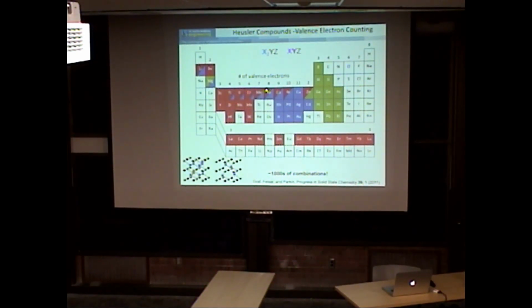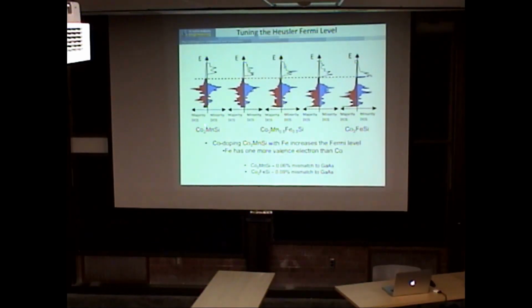If I do cobalt-2 manganese silicon, what happens if I decided to add iron, say do cobalt-2 iron silicon? I've added one valence electron to the formula unit if I did that, or go in between. In fact, we could go in between. Let's just add iron, mixing sort of manganese. I should be able to go from cobalt-2 manganese silicon to cobalt-2 iron silicon. And if I think of this as just adding electrons, all I'm doing is move the Fermi level up.